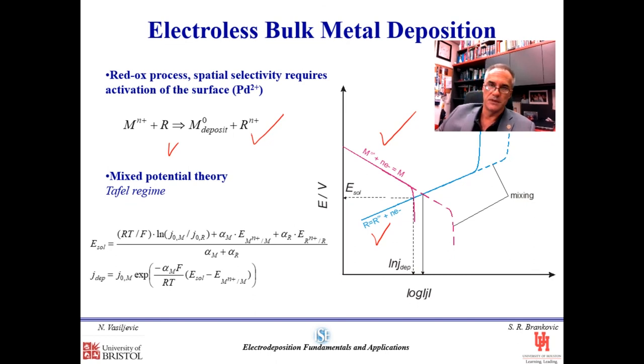And if they both, for example, follow the Tafel regime, then we can go through certain basic math and describe the solution potential in terms of the kinetic parameters of the electro-reduction of our metal and electro-oxidation of our reducing agent, and then we can also estimate the deposition rate of our electroless process, which in this case is reflected in this current density that we can calculate.